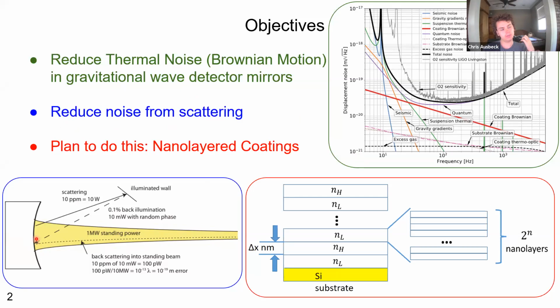And that coating has crystals in it, and these crystals can cause some of the photons to scatter out. By itself this doesn't really cause a significant noise to appear. However, the main problem is that some of these photons then scatter back into the mirrors. These photons are now at a different phase, and so they contribute a very large phase noise to the mirrors. Our current nanolayer coatings start with a silicon substrate, and then we have different low and high index materials that are nanolayered together with some change in X between them. In this case, we have a low and high index, but these could also be two high indexes as well.